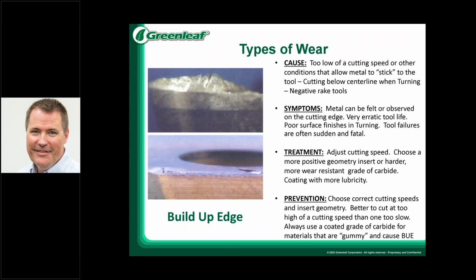The last type of wear I wanted to address was the built-up edge. This is common in more ductile materials, even into looking at stainless steels. You'll see where the materials are somewhat sticky, and if you don't have enough of a positive cutting edge, the material will start to build up. The top image shows a very dramatic amount of built-up edge on it.